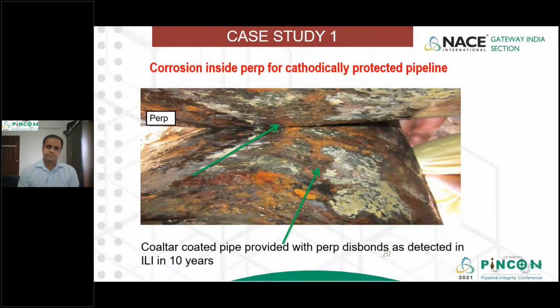This is a simple case wherein perps, I hope you are aware, perps are small coating patches which are used during projects to fill up the holidays which we observed in the holiday survey in the laying part. These perps are nothing but a separate layer of coating rubber which is not equivalent to the mother rubber. So what happens is the coal tar coated pipes are sometimes provided with perps, and the perps are disbonded with aging because they don't get adhesion properly, because these are two different coating materials. So this has given rise to corrosion.